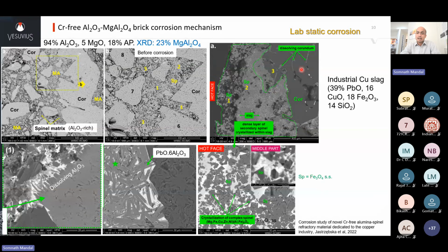And you see something very concerning. You see the slag is directly dissolving your alumina grains. And what you have in the slag is this complex spinel, magnetite forming a solid solution with the leached out alumina. And then you see that close to the refractory, at the interface, you see this lead hexaluminate. This is like your CA6 phase, very well known in the refractory castable world. This is an analog of that, lead hexaluminate, and this is directly dissolving out these large alumina grains.